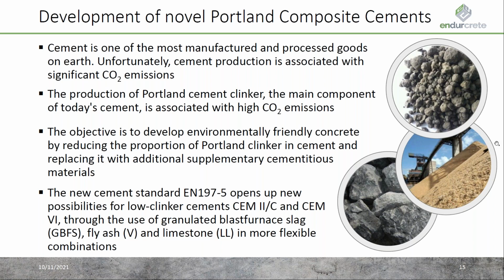Thank you very much. I would like to present you the composite cement activity at Heidelberg Cement. As mentioned before by Arnaud, we have to look at opportunities to reduce the clinker content in the Portland cement, because the clinker production is associated with a high CO2 emission. And the new standard EN 197 Part 5 of the European Cement Standard gives us a lot more possibilities, compared to EN 197 Part 1, to lower the clinker factor or clinker content in the cements.